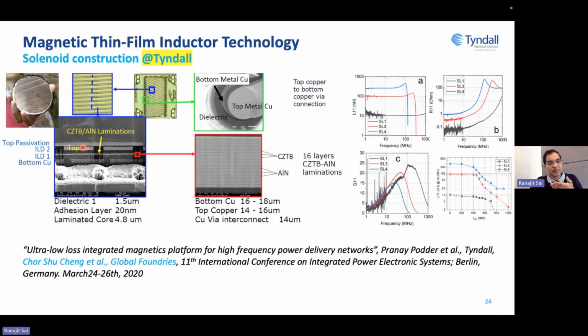This is the solenoid top copper, and these are the bottom copper, and in between top and bottom, with some passivation separation, you have a magnetic thin layer which is about 5 microns, or rather 4 microns thick, and this thickness is actually comprised of very thin lamination structures.